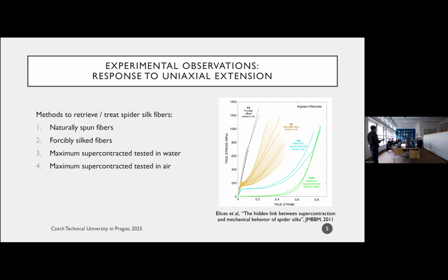If you take this naturally spun fiber, you put it in an aqueous bath, and then you test it in water, you end up with this green curve here. So this is what we call maximum supercontraction, obtained naturally, and we stretch it in water. This curve here is a very typical response of rubbers, right? So this is what rubbers do. And if you take this fiber out of the bath and you put it on the table and you let it dehydrate completely, after it's dry, and then you test it, you end up with the blue curve, which means again we're back to this kind of typical glassy polymer behavior. Another method of getting a spider silk fiber is what we call forcibly silking.